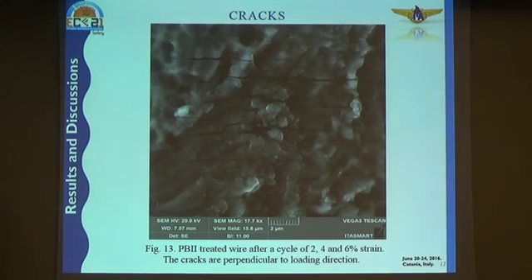the micrograph of the stress strain wire, we saw a lot of cracks perpendicular to the strain, to the loading direction. So what is happening here is that we have a bulk of nickel titanium with shape memory effect, and we have a surface with chemically changed composition. So in the surface, we don't have a shape memory effect. And when we stress the material and we deform it, it cracks. Of course, in these applications, we do not intend to make a large deformation in the materials. But it's not a good idea to have this crack.